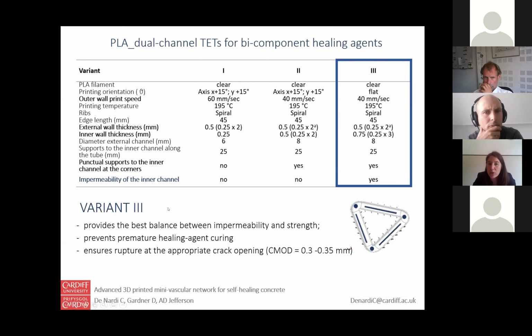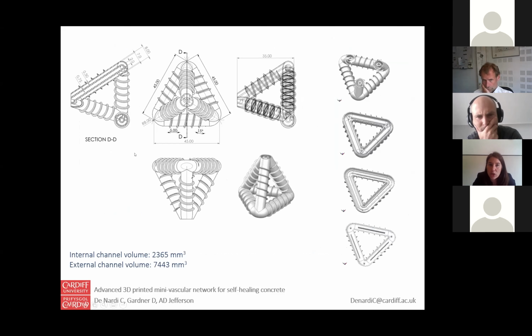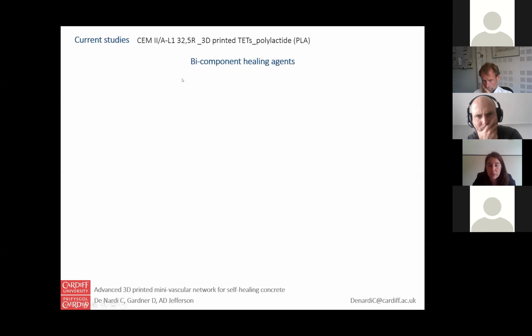It provides a very good balance between the strength, so we reach the point to break when we want, and the impermeability. It prevents the premature healing curing, and then we rupture at the appropriate crack opening. Here again, the complete drawings of the dual channel TETs. On the right, you have 4 steps of the printing. Basically, the proportion between the inner channel volume and the external one is 1 to 3.